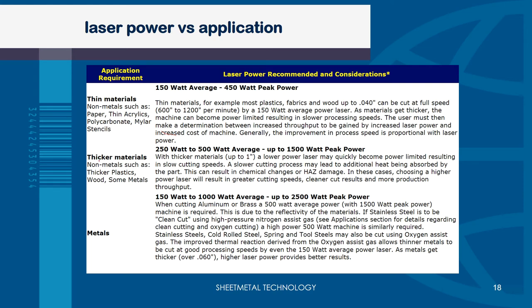If you're cutting thicker materials, also non-metal, such as thicker plastics, wood, and some metals, up to 1 inch or about 25.4 millimeter, you can go from 250 to 1500 watt power. This may result in slower cutting speed. The slower cutting process may lead to additional heat being absorbed by the part, resulting in larger heat affected zone damage.